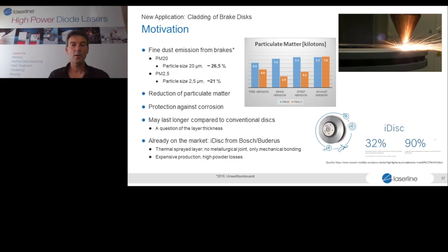And one way of reducing the fine dust that is produced from brake discs that are not clad or treated in some way is what we are trying to address. There's already a solution that exists. To my knowledge, it's used for the Porsche Panamera only. That's the iDisc from Bosch and Buderus. It's a thermal spray layer, and as I mentioned before, this is simple mechanical bonding, and also requires quite a lot of powder. So it's a less efficient process than what we are trying to find with the laser process.